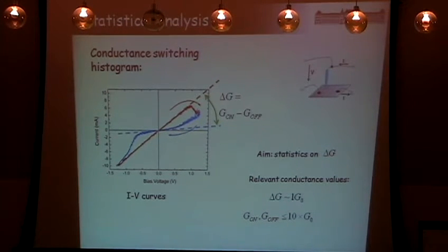It's the current density that counts. But you don't really have Joule heating anymore if you have a contact size that's smaller than the inelastic mean free path. No, it's not true. It's the current density that counts. You have very few atoms, so you drive a large current in a very small area. So the number of scattering events per unit time and unit volume is enormous.